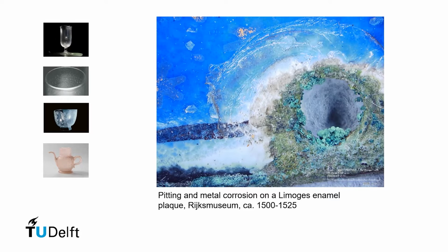So what happened is that the dissolved salts interact with the moisture and the metal to form these very peculiar corrosion products, which you only find where the combination of these materials, glass that's deteriorating and metal, is present. That's when these corrosion products form, and they are very exotic and quite beautiful, some might say. So these are all examples of advanced stages of degradation, but in order to understand what is going on, we need to take a step back and look at the basic chemistry of glass. So next slide, please.